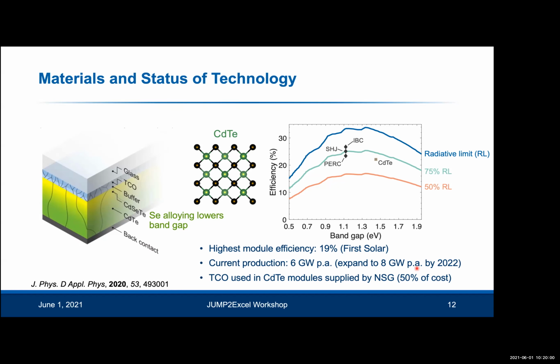Although the UK doesn't itself manufacture cadmium telluride solar cells, one of the British companies, NSG, which used to be called Pilkington, makes the transparent conducting oxide coated glass, which is used in cadmium telluride solar cells. And that's quite significant because this TCO coated glass accounts for 50% of the cost of the solar cell.